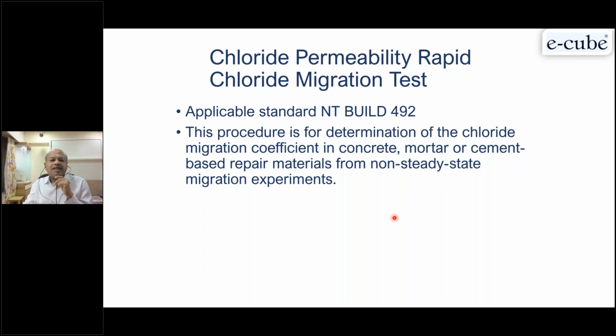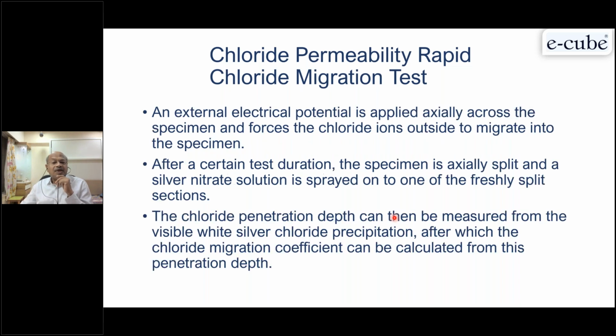It is a real test for this and it is very difficult to achieve those parameters. So again, same thing, you put that voltage for that duration, whatever is given in the table as per the specimen, and then you split it. Once you split it, you spray the silver nitrate and you see the actual chloride movement in the specimen. There, we only depend upon the coulomb value. Here you can see really how much chlorides have penetrated.